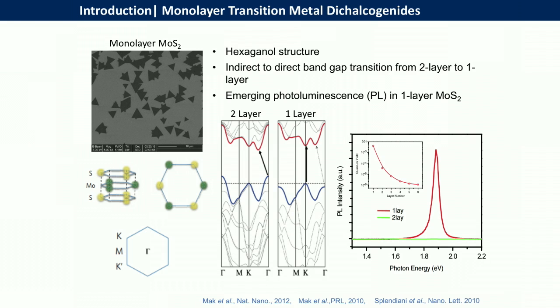So in the last 6-7 years, as many of you know, there's a lot of interest, and this university has done pioneering work, especially from Xiaodong Xu's lab, in a new class of materials called transition metal dichalcogenides. These are layered materials, and you can exfoliate them like graphene. When you get down to a monolayer, just a MoS2 monolayer, it's actually three layers: one sulfur, one Mo, and then another sulfur layer. In these two-dimensional semiconductors, when you go from few layers to one layer, the material undergoes a transition from an indirect bandgap semiconductor to a direct bandgap semiconductor. So the moment you go to the monolayer limit, it starts to emit light.